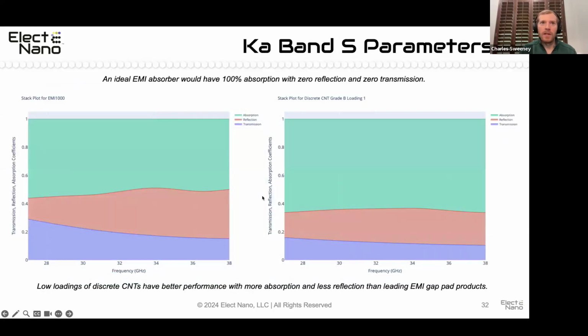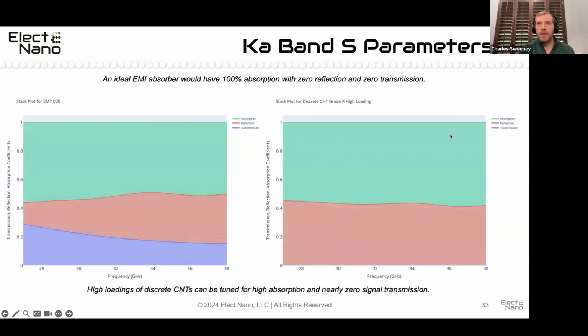And then when we look at this, it basically tells you what fraction of the wave is being absorbed, reflected, or transmitted. This is the control material over here. And so for a very low loading of carbon nanotubes, we're doing better in terms of overall absorption. We're reflecting less of the signal and transmitting less of the signal. And then if we go to the higher loading levels, again, it's really cool because effectively you're transmitting zero signal, 0.001% of the signal remains transmitted. A lot of it's being absorbed, and then some of it's being reflected.